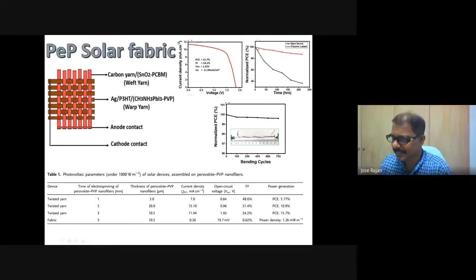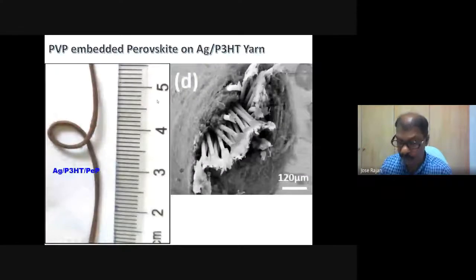There are some microscopic and macroscopic images, photos and microscope images. We have nearly 2 volts from this fiber of about 5.5 centimeter long and about 300 micron thick. When we made several twists, we did so many experiments. The details are in that publication in Solar RRL, you can refer to them. We have efficiency as high as 15.7 in yarns.